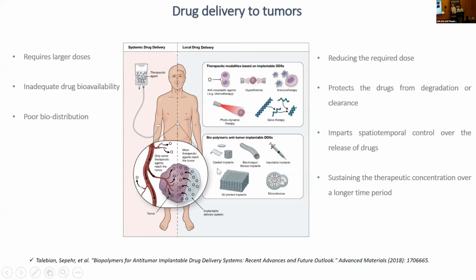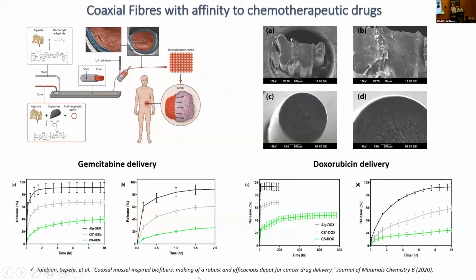Along these lines, we next decided to use coaxial wet spun fibers, and we also included certain chemistries into the fibers. What we hypothesized was that if we use this molecule dopamine, which is a catechol, and attach it to the hydrogel alginate, we would get dopamine functionalized alginate, which would have some adhesive properties that can give us some affinity towards these drugs, aiming to prolong the release of these drugs.